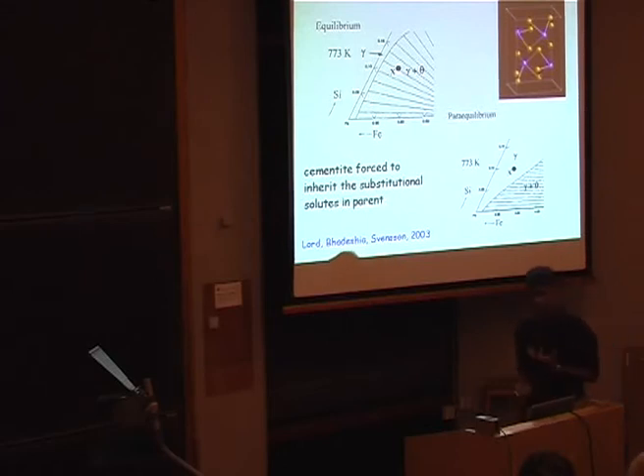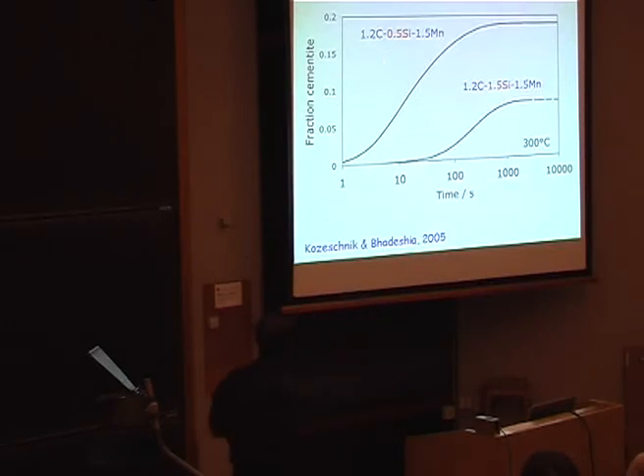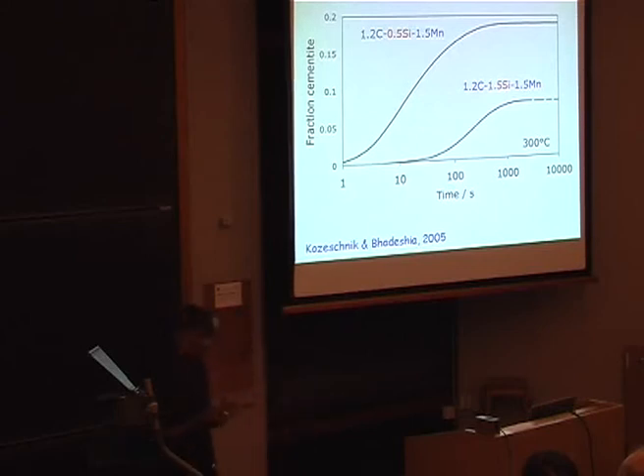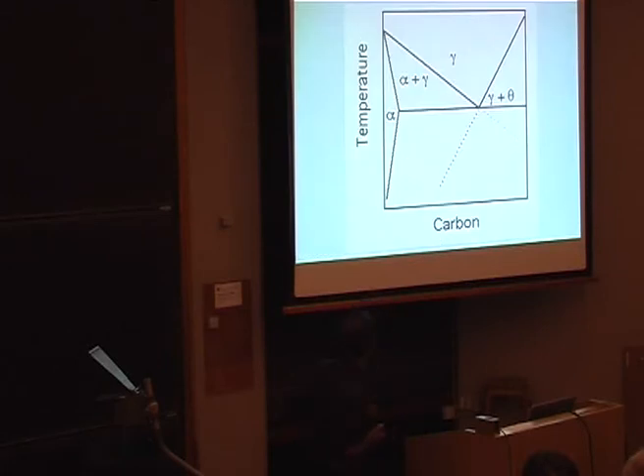And some very elementary modeling shows you the effect of silicon here. So I've changed the silicon here from 0.5% to 1.5%, and you can see there's a dramatic change, not only in the kinetics, but in the equilibrium volume fraction. And by appropriate alloying, I can get rid of it altogether. So I can get rid of the brittle phase by designing the alloying elements, the sort of work that Hume-Rothery did many, many years ago.